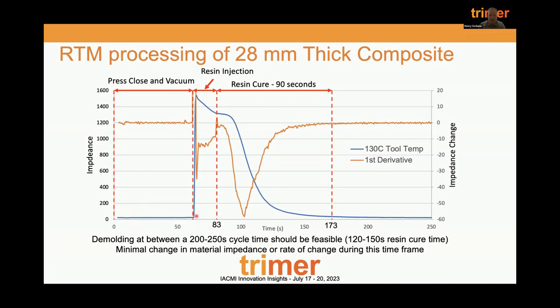There's a lot of lines here, but we have a 60-second vacuum and press closure. Resin infusion starts, we jump up in our impedance here, and this drops down as we complete the injection. This is about a 23-second injection for this part. It sits with some latency, which we dialed into the material so that we could ensure that we filled the full part. And then it snap cures, and in 90 seconds we're fully cured.